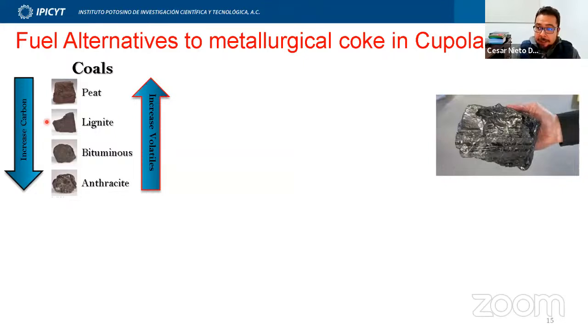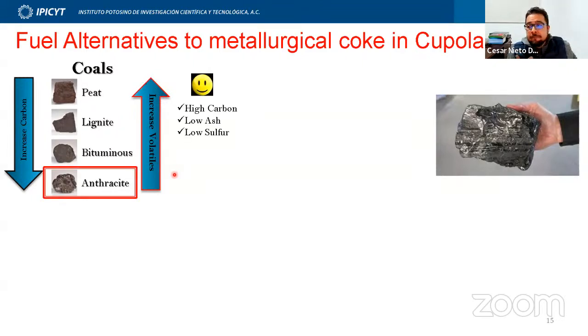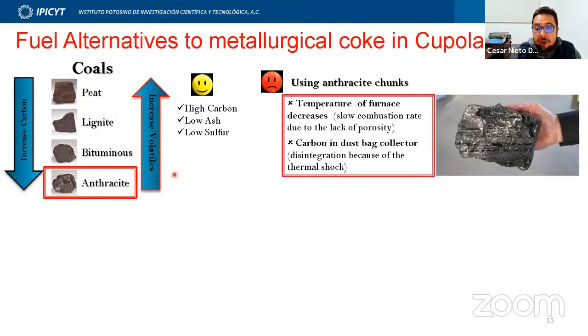When I say high rank and low rank, I mean it is based on the carbon content of the coal. Anthracite should have a carbon percentage between 90 and 95%, and for instance, peat should have around 50% carbon. In this sense, anthracite is very close in chemical composition to coke, because it has very high carbon, low ash, and there are some coal mines with very low sulfur. However, when people in the foundries try to use anthracite, mining these big chunks and just dumping them into the furnace, what they see is that the furnace temperature decreases.